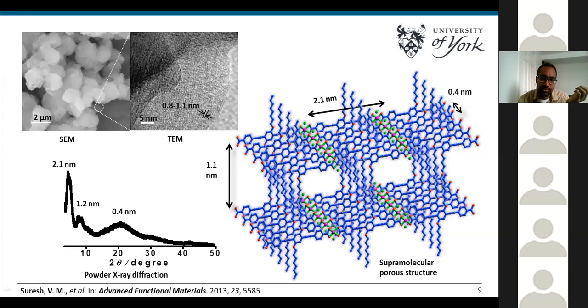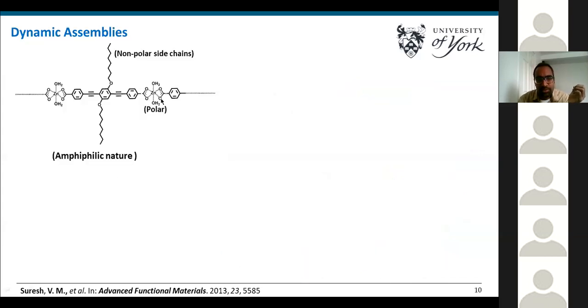So in this way, we propose this is the best possible structure from the analysis of TEM and X-ray diffraction. Now, if we carefully see, the 1D coordination chains possess polar head groups and non-polar side chains. So this whole 1D coordination chain can act as an amphiphilic system. It is known from the literature that such systems can transform into different morphologies when we choose different reaction parameters.